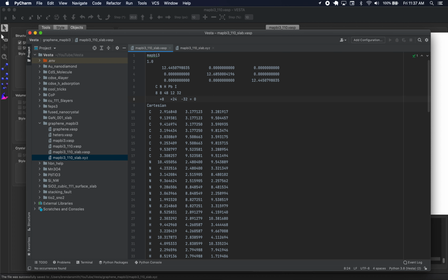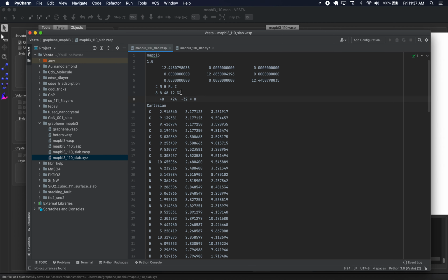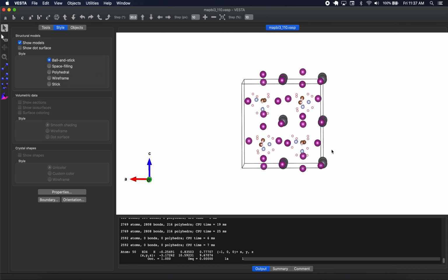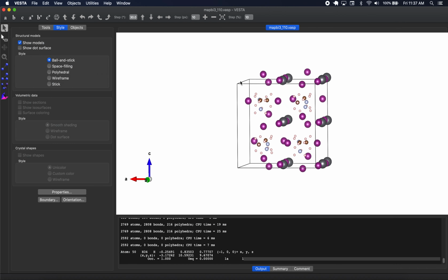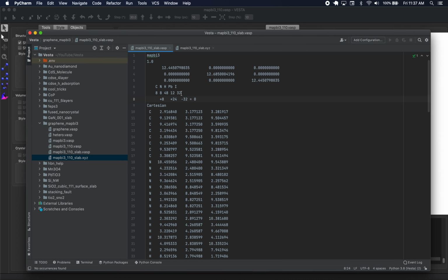This is why, if you did not include these extra iodine atoms, you wouldn't have got 32 iodine, you would have got 28. So these 4 iodine, 1, 2, 3, 4. If you didn't include those, you would have got 28 iodine, and then you would have had a plus 4 charge in your system. But when you include those iodine, you make your system charge neutral.